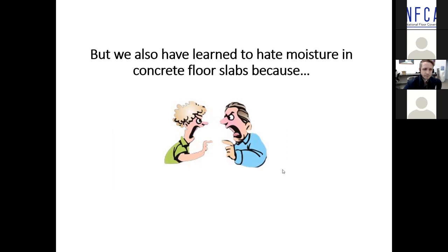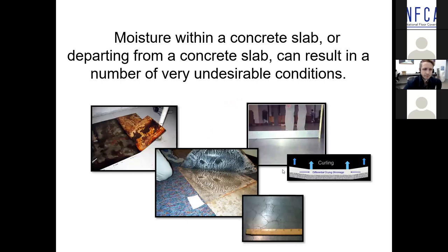Unfortunately, we have also learned to hate the very same moisture in concrete floor slabs. Why? Because moisture that's within the slab or departing from a slab can result in a vast number of very undesirable conditions. On the left, you see mold that's growing underneath a vinyl composition tile. You can see adhesive breaking down beneath a carpet tile installation that was out in Oklahoma, slab curling, and so on and so forth.